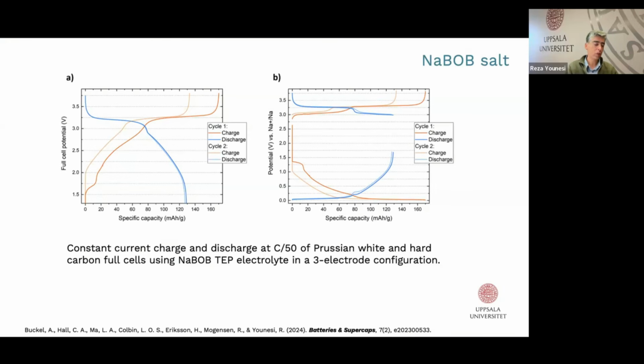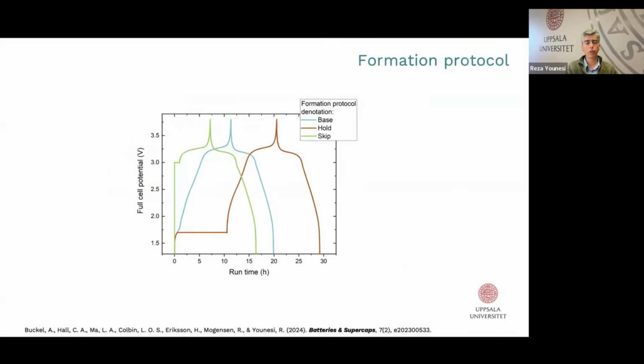Another thing we could do, and that's an interesting topic we try to understand, is the relation between this electrolyte composition and the formation protocol. Because as I mentioned, there's a very clear, distinct feature at around 1.5 to 1.7 where NaBOB decomposes. So we tried different formation protocols, as you see here.